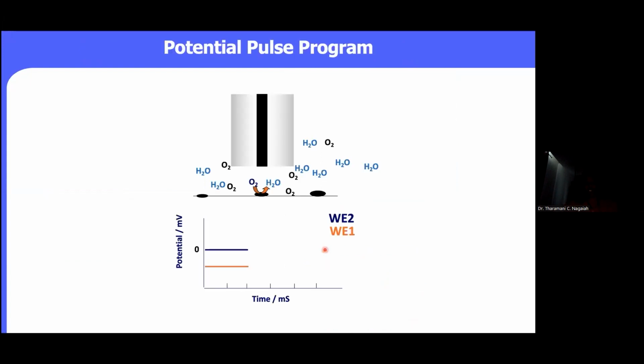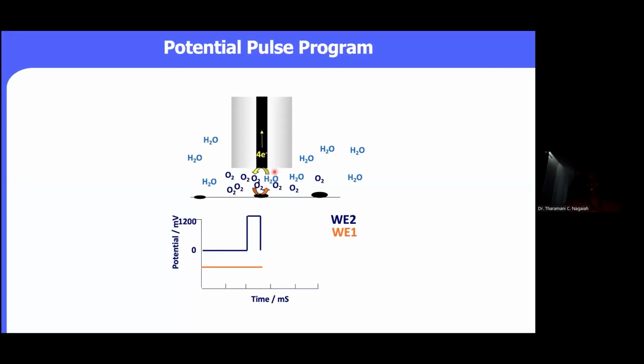So this is a potential pulse program. I have given an example in the case of the buffer media. So what we do is that you can see the orange color and also the blue color here. So we continuously polarize the samples where oxygen is reducing to the water. And at the working electrode, we are trying to give the pulse profile. What we do here is that oxygen reduction reaction, that means we need the oxygen in the solution.